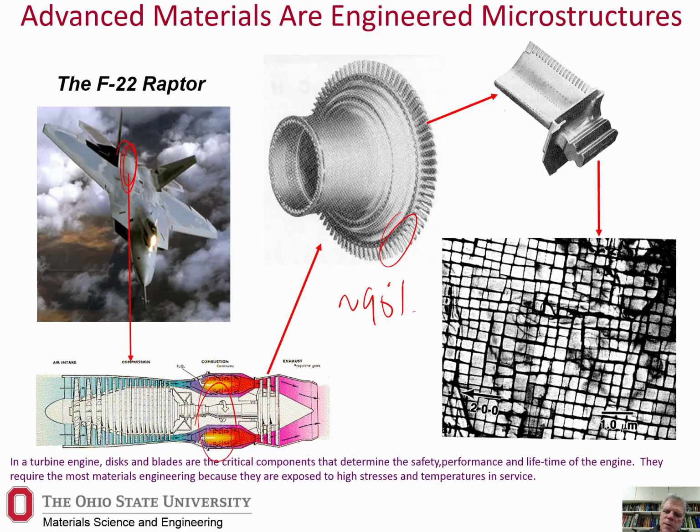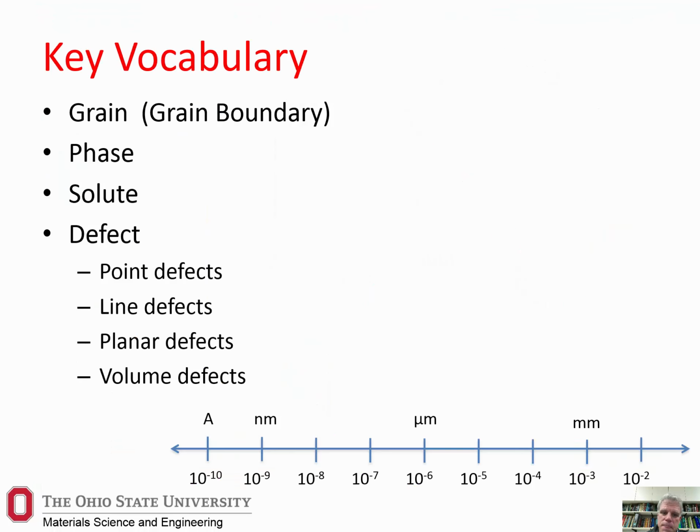The way we do that is by making these structures, which we call gamma prime structures, where, for example, the gamma is nickel, and then the gamma prime is Ni3Al, and the gamma prime are these little guys here. And by heating the material to high temperature, quenching it down, aging it just right, we can make these remarkable structures that have remarkable high temperature strength.